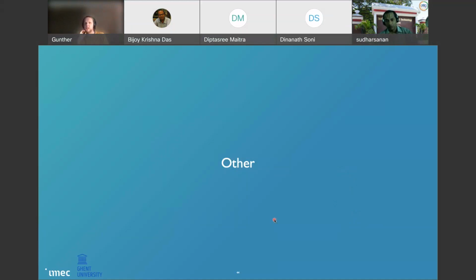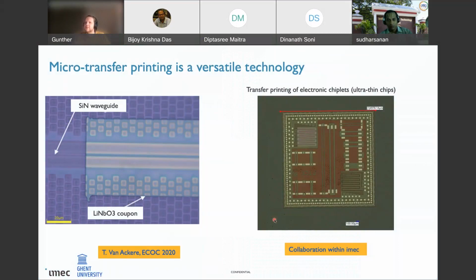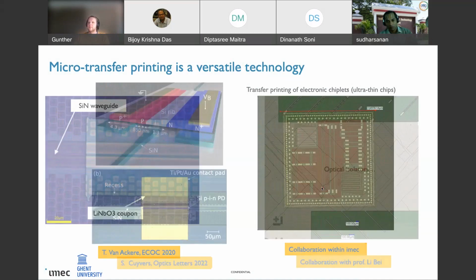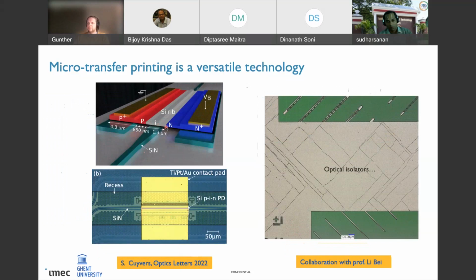Then in just two slides I want to summarize to show that this microtransfer printing is actually a very versatile technology. Every material or device that you can release from a substrate can in principle be transfer printed. So you see some examples here of other things we do. Transfer printing of lithium niobate on silicon nitride waveguides. But as mentioned before, also transfer printing of electronic chiplets on silicon photonics. Silicon active components fabricated on an SOI platform. We can transfer print, for example, silicon nitride. And some early work, as you can see from the picture, is trying to transfer print magneto-optic materials from a source wafer to a silicon photonics target wafer to build integrated optical isolators.